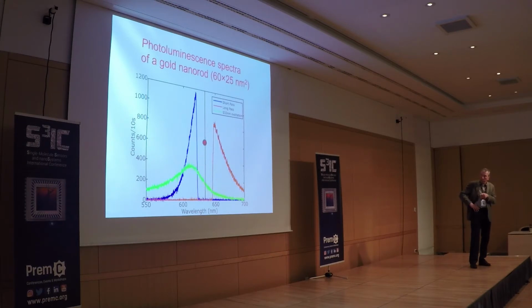So we took here a nanorod which absorbs just at 600, and our laser is in the red wing of this plasmon resonance. That means that the enhancement is mostly active on the blue side of the line. And that means that it enhances the anti-Stokes with respect to the Stokes. And that's very nice because now we have this anti-Stokes luminescence, which, as you imagine, is temperature dependent.